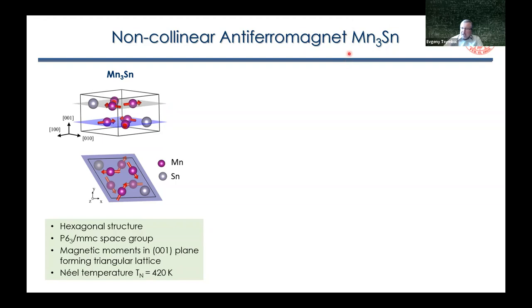In particular, it was shown that the symmetry of this antiferromagnet is such that it allows the anomalous Hall effect. So by symmetry, it has an uncompensated magnetic moment. This is, by the way, different from ruthenium oxide, which doesn't have an uncompensated magnetic moment. And it has the anomalous Hall effect. So manganese 3 tin has a hexagonal structure. It has magnetic moments in the 0001 plane. They're forming a triangular lattice and rotated by 120 degrees, making this antiferromagnet non-collinear.